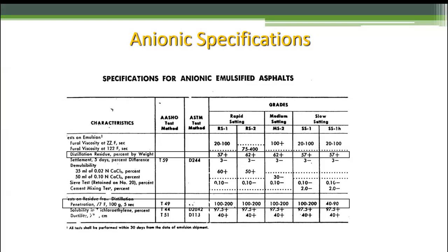So again, remember, because a lot of times with tack coat, what do we use for tack coat? That bond between two layers. We shoot an SS, a slow set, right? First step in a paving overlay job, you got to clean the road. Next step is you got to shoot the tack. Next step is we got to wait till the tack breaks. Now we can start paving.